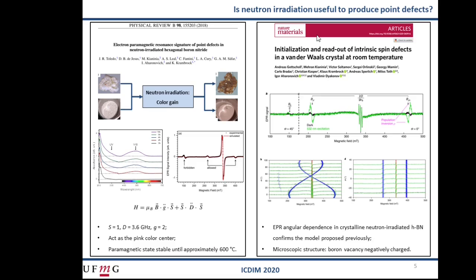Another research group, also using EPR measurements, determined that this high-spin center is associated with a boron vacancy in a negative charge state. Note that its EPR spectrum is very sensitive to green illumination, confirming that this absorption band here in the visible region is in fact of the spin-1 defect.